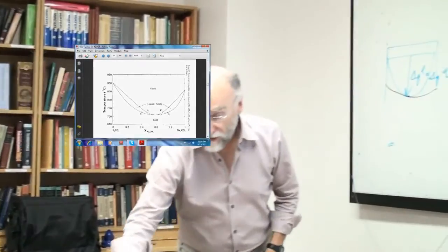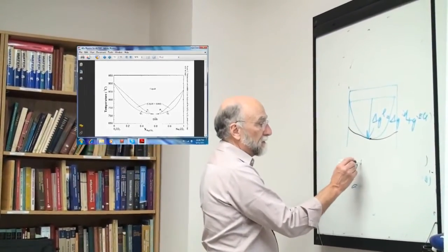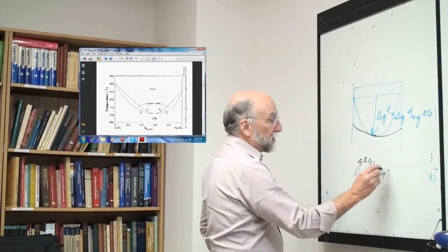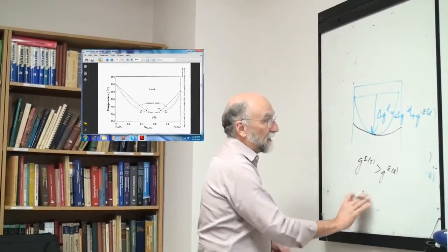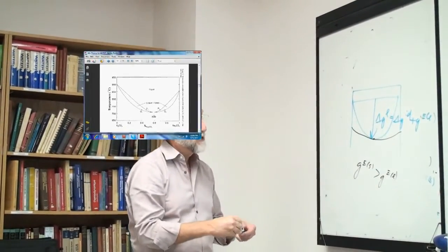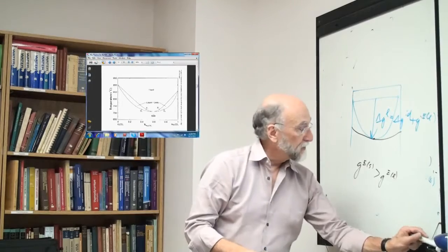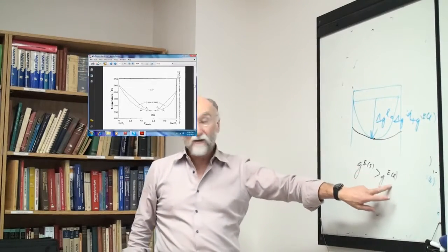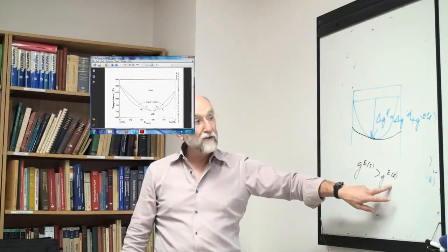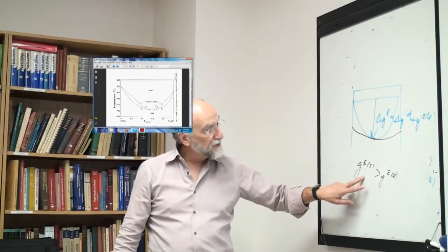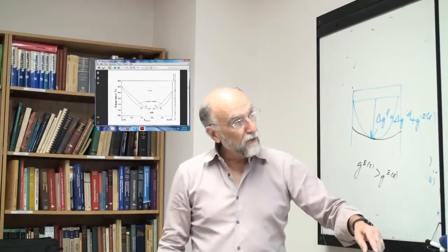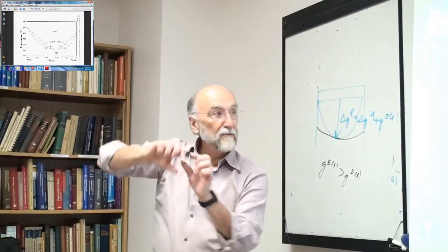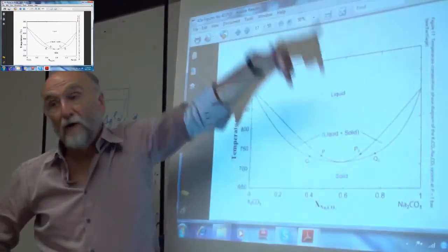Now that occurs because G excess solid is greater than G excess liquid. That gives you a flatter G excess solid curve and results in this. This of course means that the solid is less stable than the liquid, both relative to ideal solutions. So you've stabilized the liquid relative to the solid. So it's like you have the two-phase region in the germanium silicon system and you push it down in the middle.